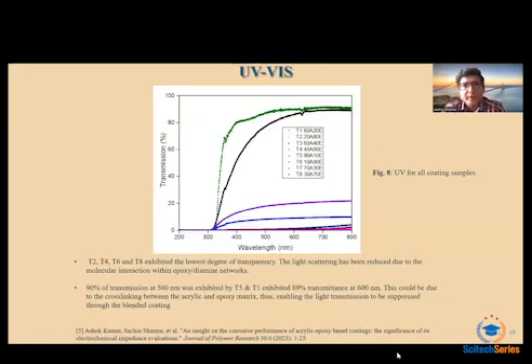Okay, so the next one is the UV-Vis spectroscopy, and it was indicated over here that the T1 and T5 samples, which, on an important note, contained higher content of acrylic resin, which is 80A20E and 90A10E, exhibited the highest optical transparency value from 300 up to 800 nanometers in wavelength. However, the lowest degree of transparency was exhibited by the T2, T4, T6, and T8 samples, and this light scattering, which was reduced, was due to the molecular interactions within the epoxy and diamine networks.